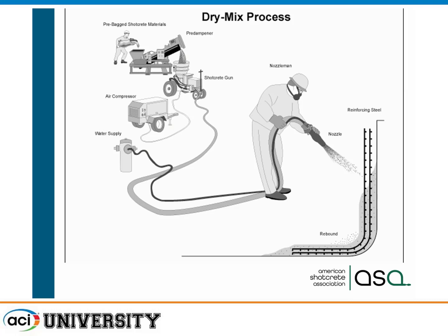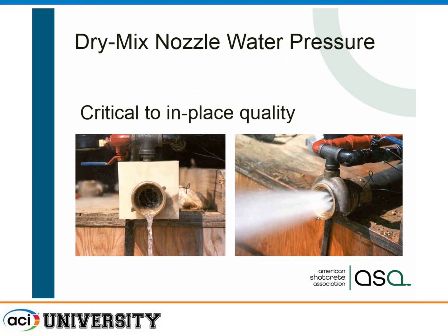That's where we basically take dry materials. So we're taking this encased bag materials with a pre-dampener, putting it into a gun, using air to convey it pneumatically through the hose, and then we use a high-pressure water source to hydrate that dry material right at the nozzle. So this is where we make the concrete. And in the nozzle, you can see here what we're doing. We're atomizing that water. We're forcing the dry material through, and that is where we actually make the concrete. We're adding water to start the hydration process. We get mixing in the nozzle. We get mixing as it flows through the air, and then certainly even completing the mixing when it impacts on the surface.